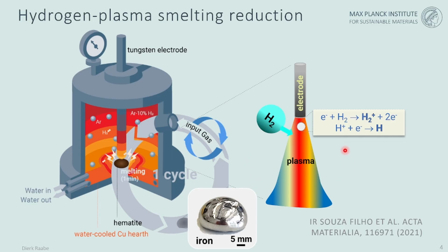And the electrons that you are charging, depending on the current density, bring the H2, which typically has only a content of 5 to 10% in the reactor, into an excited state. That means something like H2+ or H, even protons are possible, although the main occupation in a typical laboratory environment would be the atomic hydrogen, which makes the system much, much more reactive in terms of its reductant capacity compared to the molecular hydrogen. And then you can produce, as you see here, for instance, from hematite, pure iron within a few minutes. So it's a very, very efficient process.